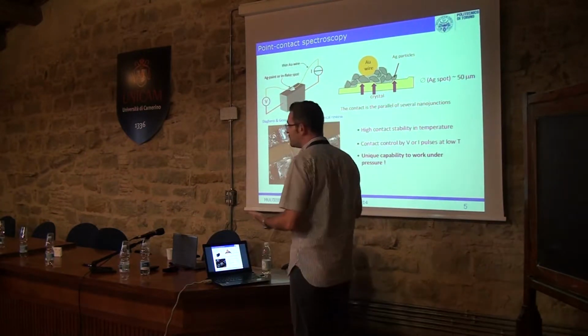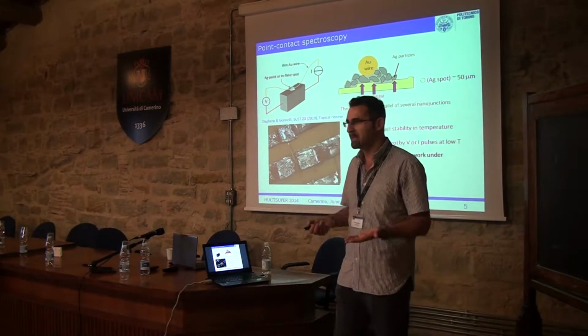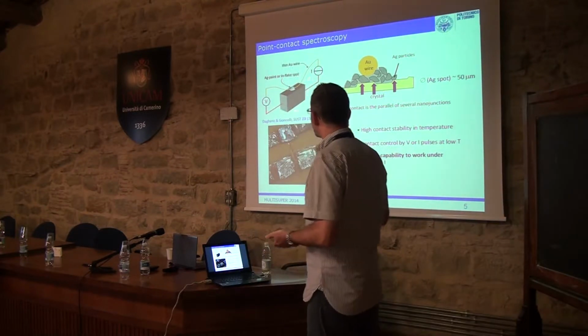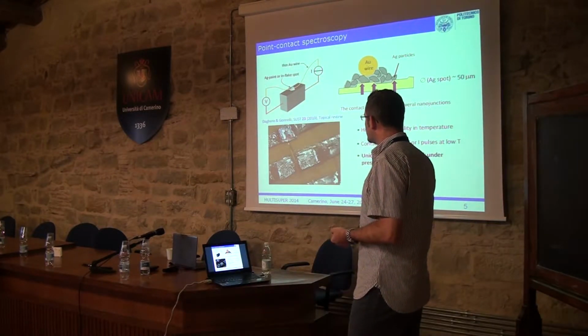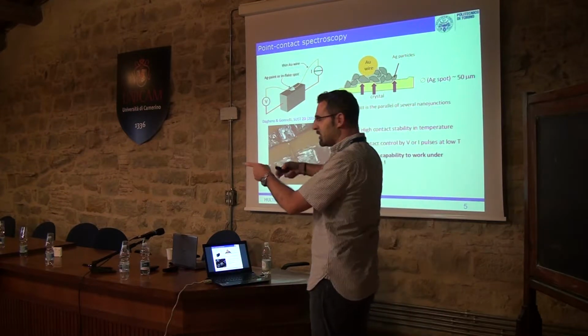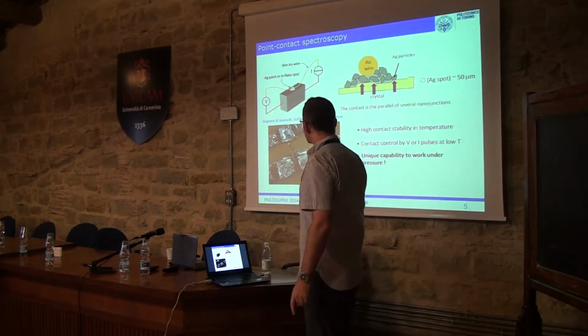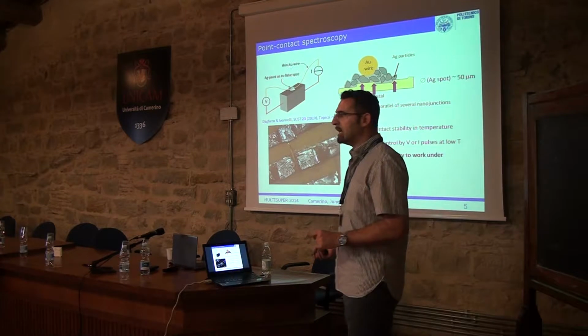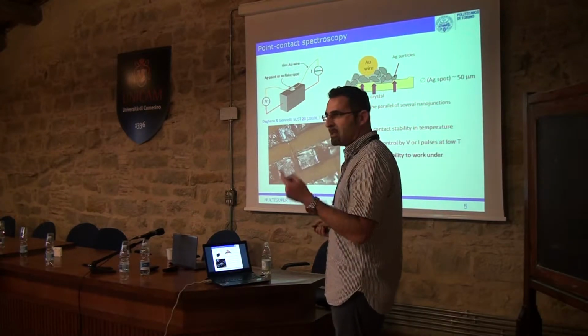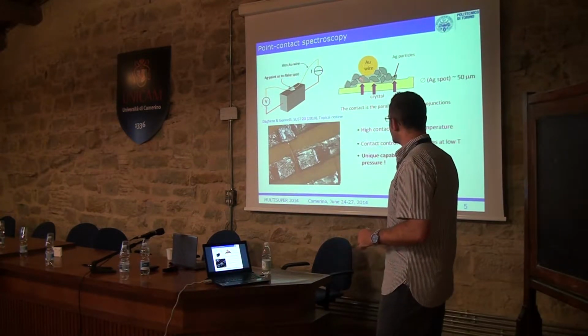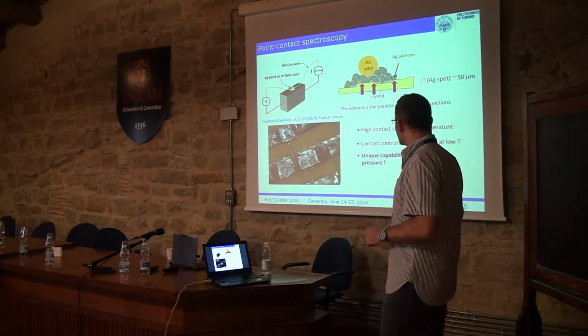It consists simply in making a small contact between a normal metal and a superconductor. We use what's called the soft technique, in which a gold wire is stretched across the sample surface and kept in place by a small drop of silver paste. In this case, the contact is actually a network of contacts established between single silver grains and the crystal surface.